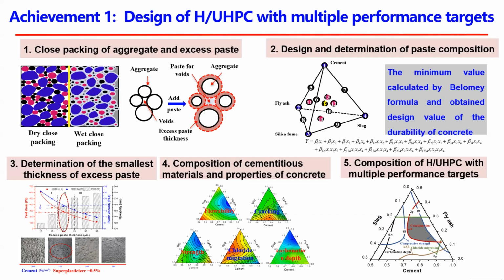And I give you five ternary diagrams here. Because if we have four compositions, you will get a contour plane, not a curve. In the majority of cases, we usually use cement, slag, and fly ash. So here I use the ternary diagram as an example. You can see we get the ternary diagram for compressive strength, for workability, for carbonation resistance, for shrinkage, or for alkali-silica reaction expansion, whatever you have.